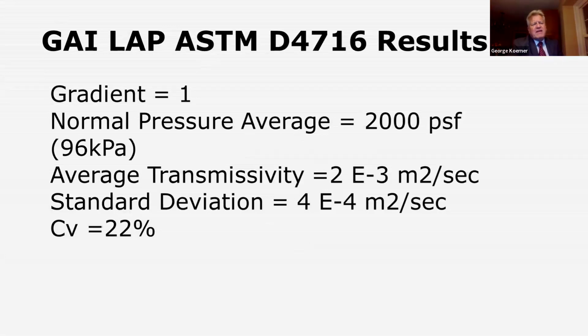The pressure was about 96 kPa. The transmissivity was 2 times 10 to the minus 3 meters squared per second. Standard deviation was almost an order of magnitude less, and the coefficient of variation was 22. We had over 25 laboratories participate in this proficiency test program. Again, the coefficient of variation was a little bit larger, but these are flow tests rather than tensile tests, and the variation has shown itself to be larger with respect to time.